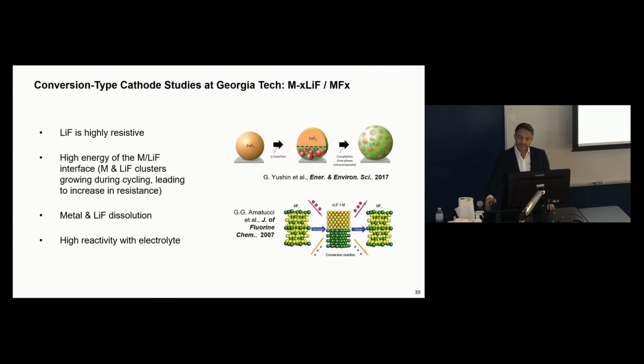Now, the next material which I want to mention for the conversion chemistry is metal fluorides. It's a true conversion, so essentially if you start with metal fluoride and you lithiate it, you produce a nanocomposite. You produce, in this case, lithium fluoride and iron nanocomposite. And if you look at this reaction and you want to make sure it is fully reversible, you realize it's probably very hard. How can you make it fully reversible? Lithium fluoride also has very high resistance. It's a very good dielectric material, has a high band gap, so it's very resistive.